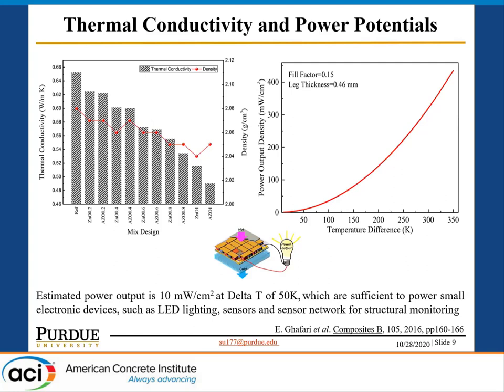And we also measured the density of each sample, and we found that the thermal conductivity is reduced with the decrease of the density. And we also did the modeling work for the thermoelectric power potential on your right hand side. So the estimated power output is 10 milliwatts per square centimeter at delta T of 50K, which is sufficient to power small electronic devices such as LED lights and sensors for structural health monitoring.